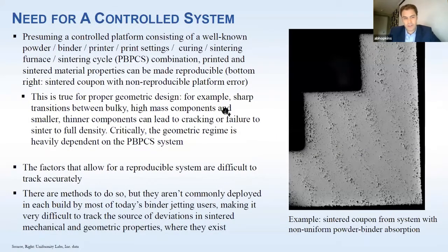All right, so jumping forward and saying, let's say we have a controlled platform. We have a well-known powder, binder, printer, print setting, curing, sintering furnace, sintering cycle combination, meaning somebody has to have developed all these parameters in windows that are robust and repeatable. That picture on the right is not a repeatable situation. That's an uncontrolled situation, not a controlled one. The pictures I showed initially of sintered materials, that's a more controlled one.